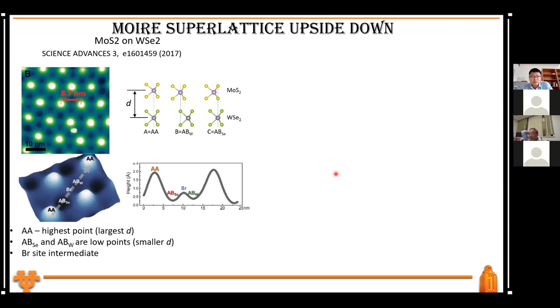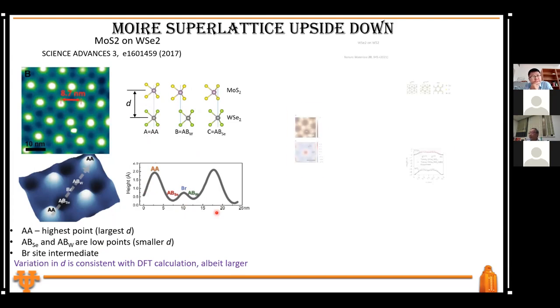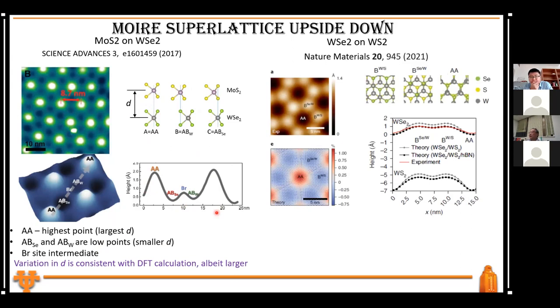Remember, in our paper in 2017, we said, well, everything seems to agree with the DFT calculation. And that, to me, is really quite astonishing. We compared this interlayer spacing, and we said, well, at least qualitatively the trend looks exactly the same. So there's no reason for us to doubt the DFT result. Until then, at the end of 2021, I saw this other STM paper. Okay, so this paper is very interesting. It looks at WSe2 on WS2.